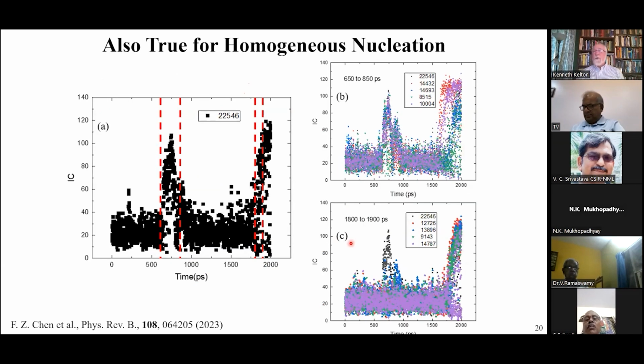This is also true for homogeneous nucleation. That was seeded nucleation. But molecular dynamics modeling now is such that you can look at such large ensembles that you can actually see nucleation events, something we couldn't do very well in the past. And here's a case, a single atom. It joined a cluster, and then it left that cluster. And then it diffused around in the liquid and then joined a different cluster.